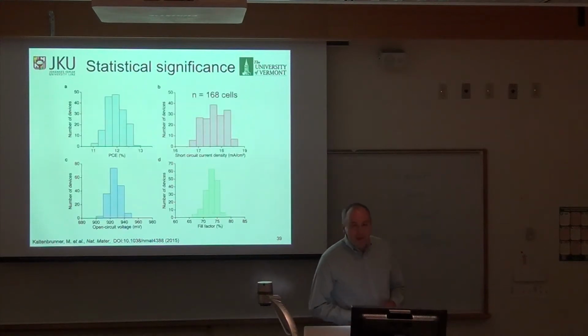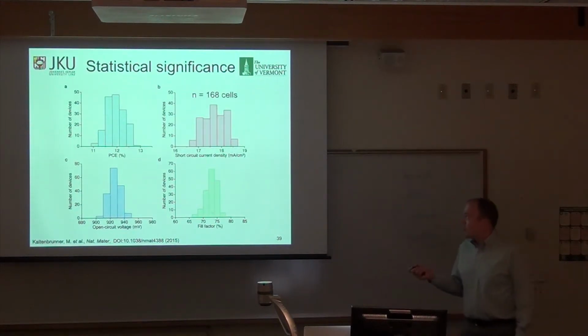But more importantly, we can make a lot of them and they all work. That's a direct result of Adam's hard work in finding a recipe for this p-dot perovskite layer to make uniform films repeatedly. Otherwise, there's no way this is possible.